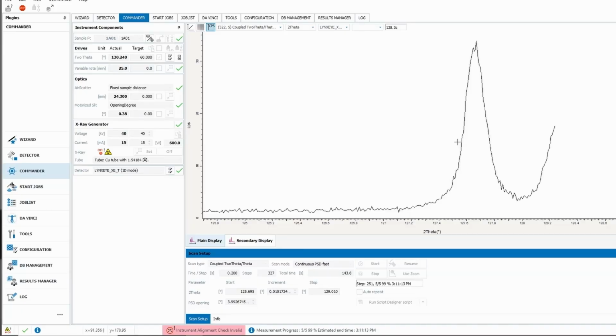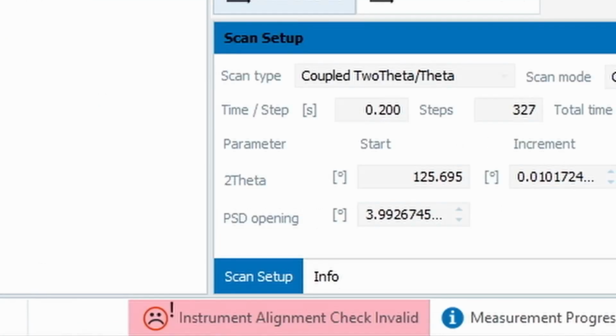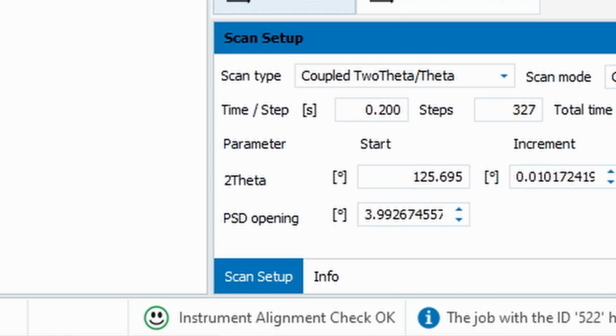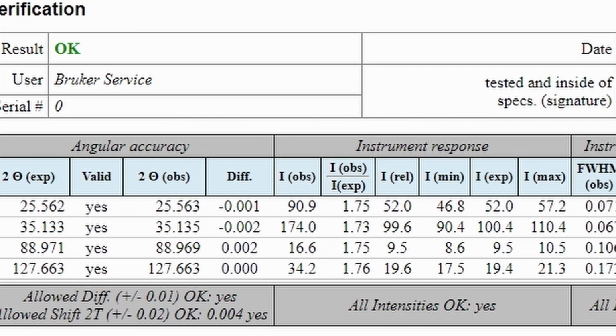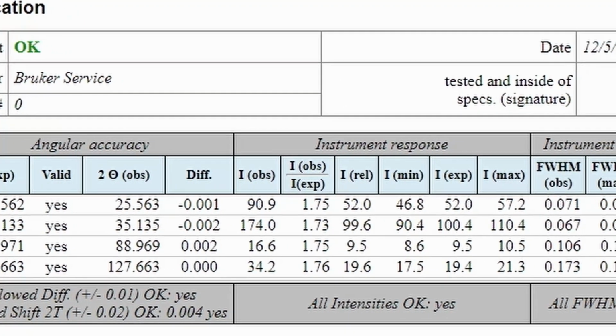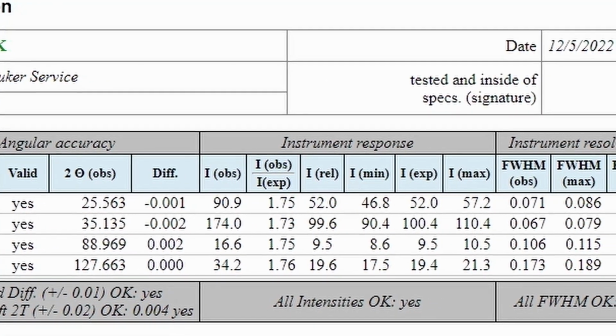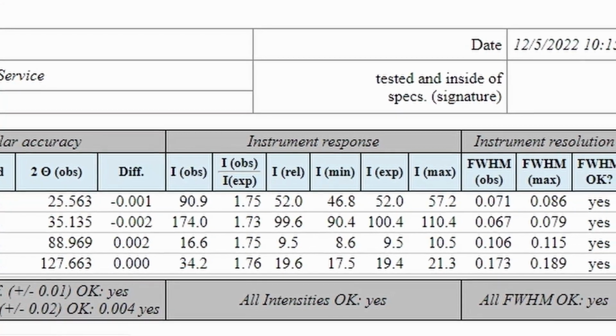In this case, the system will run through a referencing of the goniometer axis. Once this is complete, the system will confirm it is now within specification, resulting in a green smiley. The whole verification procedure follows our general acceptance protocol. Diffraction peaks of the standard corundum sample will be within 0.01 degrees 2 theta, relative intensity within 10%, and full width at half maximum less than the expected values.